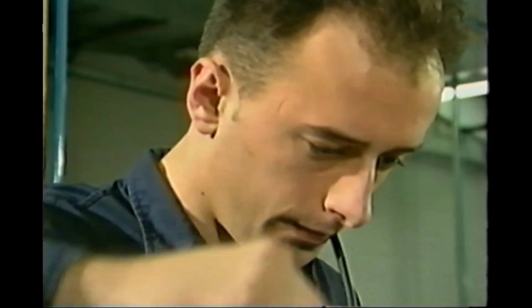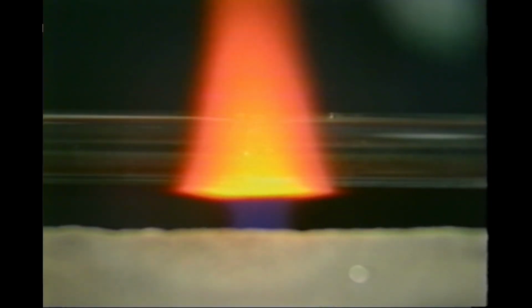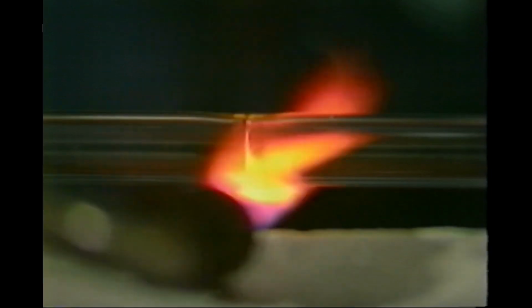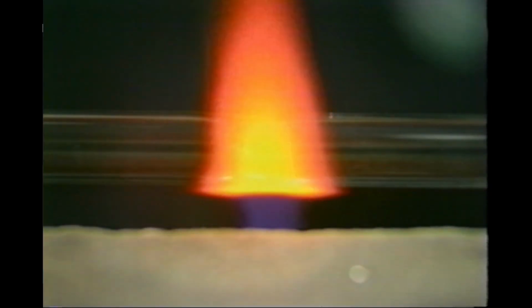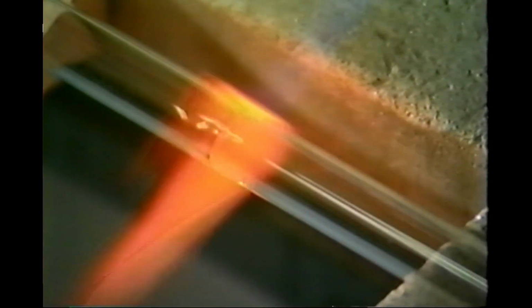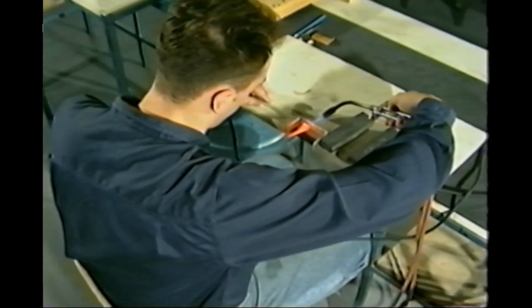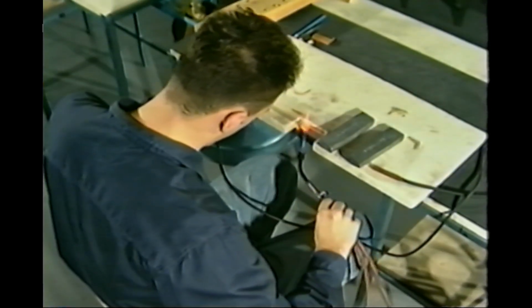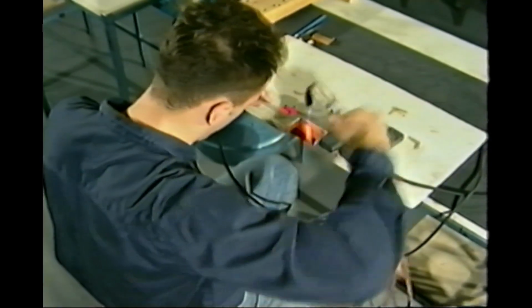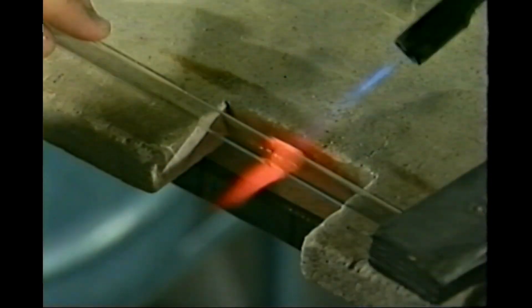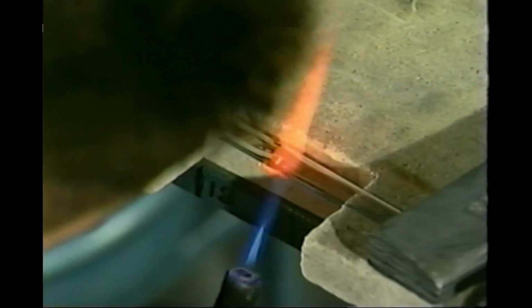The final melting operation can now be performed to smooth out the surface of the melted area and the correct diameter and glass thickness. Again, melt fully around the joint area with the same small sharp flame until a bright red heat is achieved. At this point, and just prior to giving the top of the heated area its extra melt, very slightly push the tube on the left towards the tube on the right to thicken the glass in the melt area.